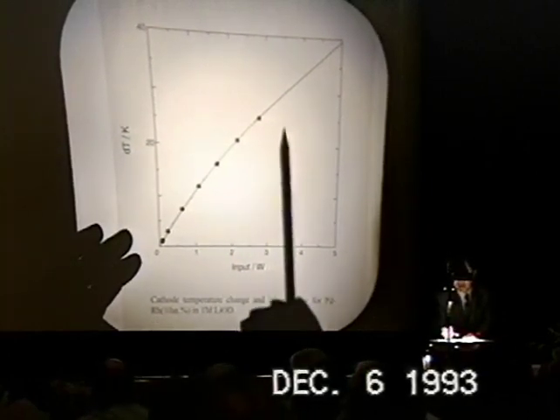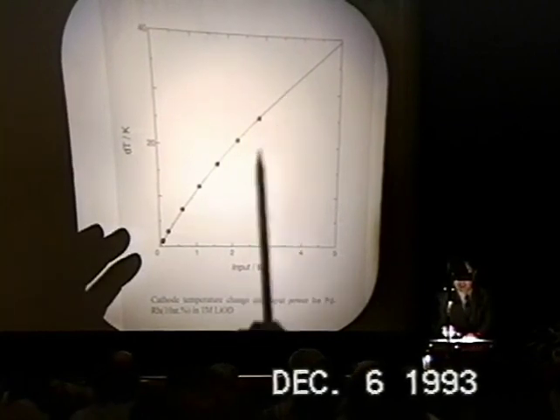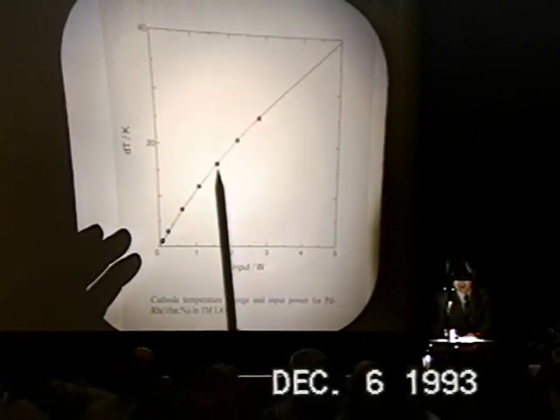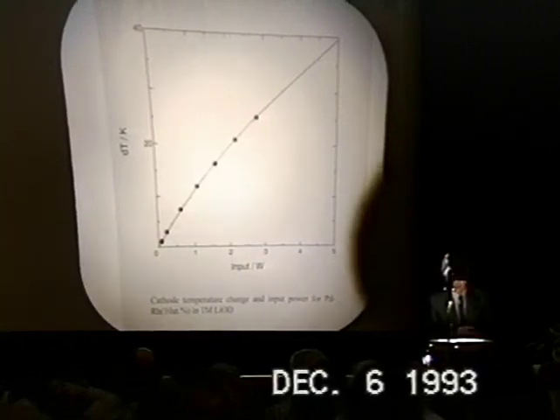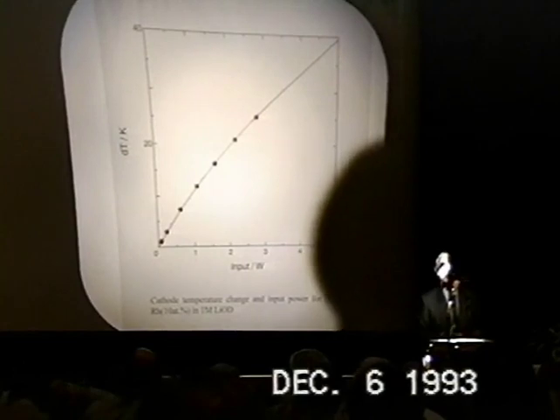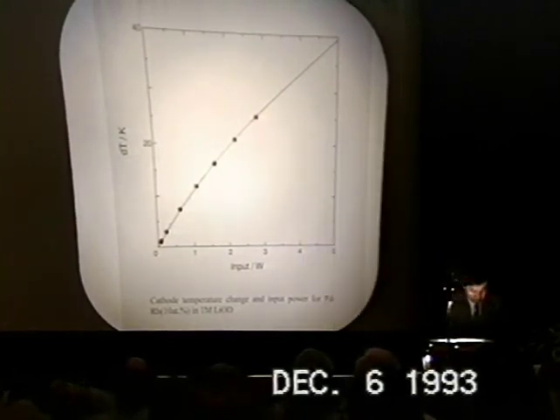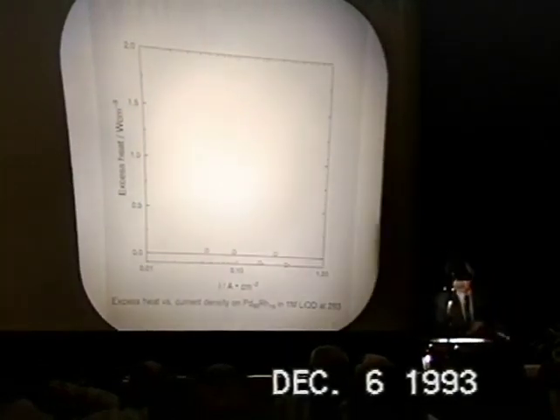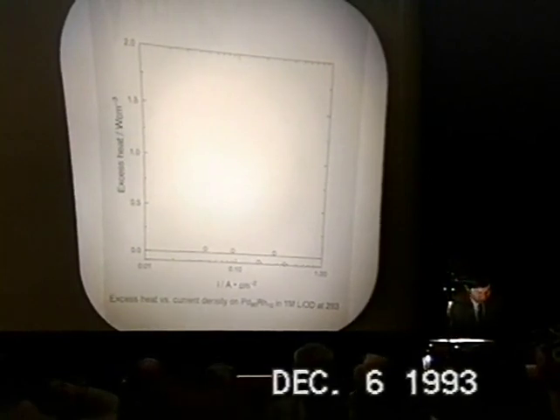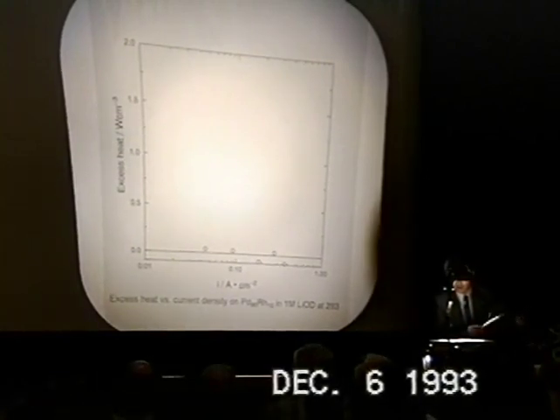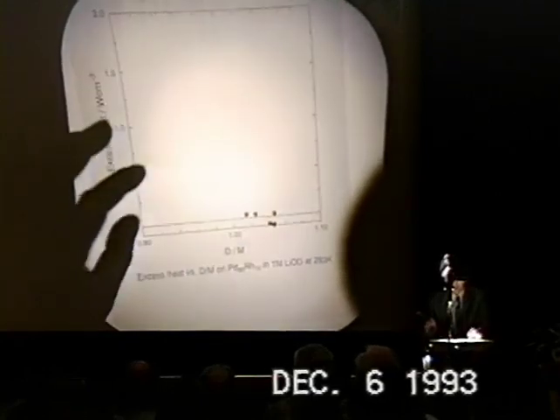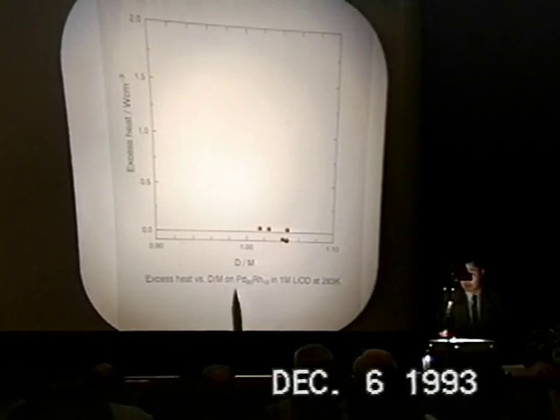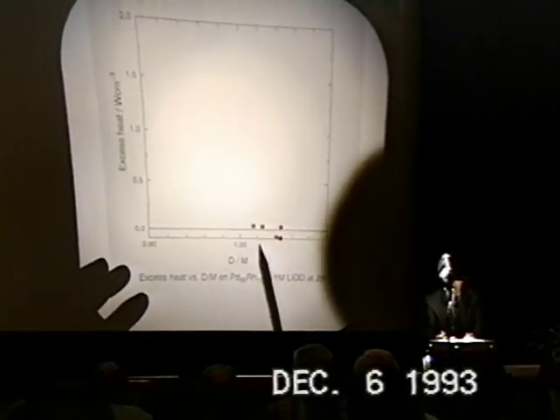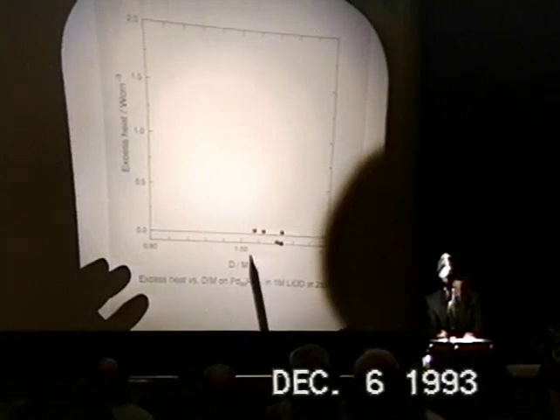I'm showing the calibration curve obtained by nickel electrode and red points observed by using palladium cathode. So the palladium is very happy to sit on the calibration curve. So if we plot the excess heat as a function of current density, we have this, no excess heat, and also if we plot as a function of D over M, again, naturally we have no excess heat in this very high loading ratio regime.